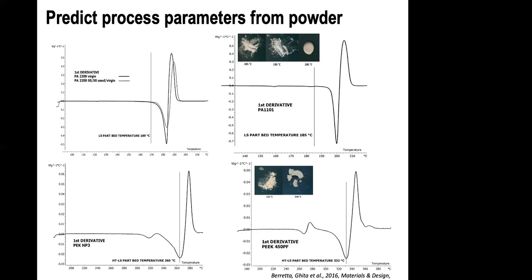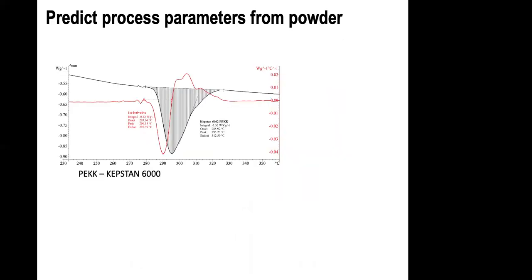But if we look at the two polyaryl ether ketone grades, PEK and PEEK, we can see that we are spot on. The bed temperature is well within the melting peak and is actually spot on the minimum of the first derivative. So that was an interesting finding. We then checked it also on a more recent grade. This is on a PEKK, Kepstan 6000, and as you can see from the picture, again, the first derivative, it's actually spot on. 290 degrees is the temperature at which the bed operates.